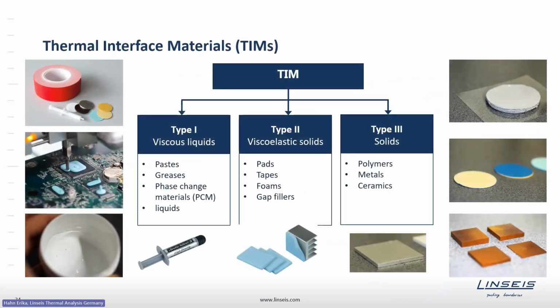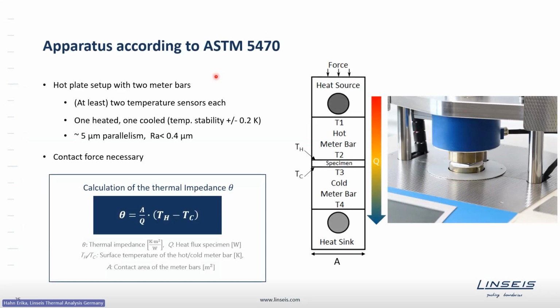For these kinds of thermal interface materials, there are three groups: type 1, type 2, and type 3. Type 1 are viscous liquids, something like pastes, greases, or phase change materials or liquids. Type 2 are foam-like materials, so soft materials like pads or gap fillers. And type 3 materials are solids like polymers, metals, or ceramics. For these kinds of examples, the TIM tester is designed. It is also a standardized method according to the ASTM D5470 norm, where this norm precisely describes how the system should be built and how the evaluation should be done.